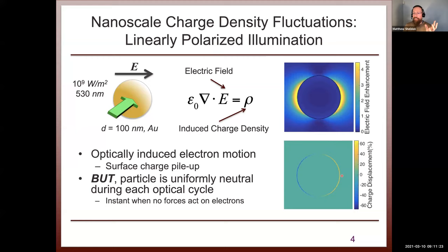I think that's a remarkable and important thing to keep in mind when understanding why plasmonic systems can give rise to remarkable behavior, if you're familiar with surface-enhanced Raman spectroscopy or some of the other strong coupling effects demonstrated in plasmonic systems. It's not that you have really great Q factors; the Q factor in this particular resonance is about 8, so there are about 8 oscillations before it rings down due to damping. But you have this huge optical density of states, due to all of these carriers being modified on the surface.